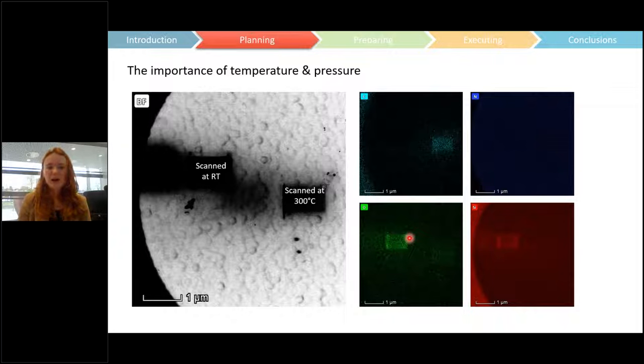That's not possible. But since then, luckily, thanks to Ninka, I found out that at a variety of universities, several independent universities have come across the same finding. So we were not going insane. This was real. If you have water at all present in your gas cell and you scan, probably what will happen is you build up this silica coating, which then means nothing happens in terms of your reaction. This is really, really important.